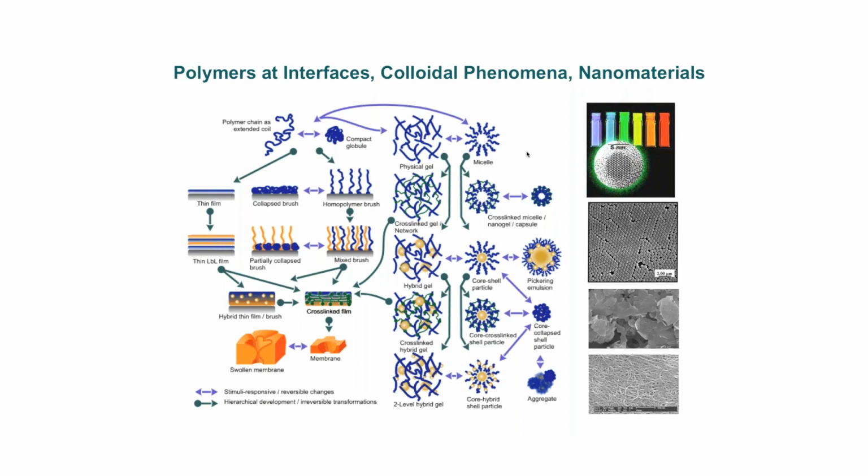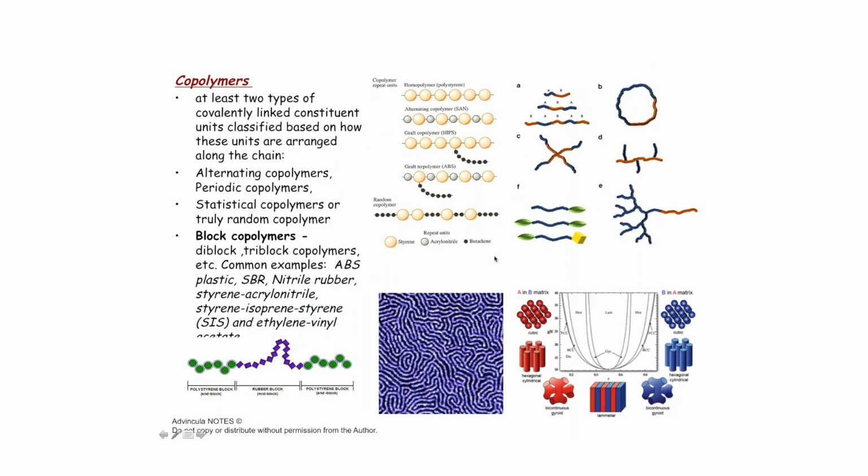Now, a lot of these are based on copolymer type of arrangements. A predominant type of copolymer that is used as a surfactant are the block copolymer linear systems. And block copolymers are, of course, found in compatibilizers, additives, elastomers. They have interesting mesophases in which you can order the chain length and the molecular weight to produce different phases such as cylindrical, lamellar, spherical, and so on.